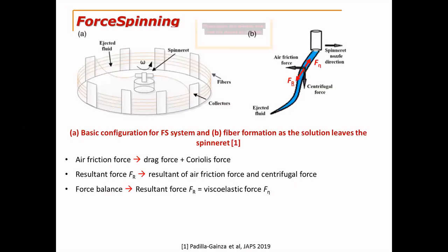Here is the schematic of the force spinning method. So as you can see here, this is the spinneret. This spinneret will be equipped with two needles. The needles can be of any size depending on the gauge. We use 28, 24 depending on the size of the fibers we need. And these are the collector plates. So we infuse the polymer solution. This equipment is particularly for polymer solution, solution-based spinning, not for melt spinning. Melt spinning has a different setup even in the force spinning equipment.